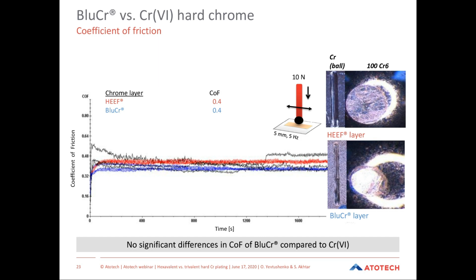This test is applied for determination of resistance to sliding, wear, and friction for non-lubricated or lubricated contacts. In this case, it was non-lubricated. For this method against a hardened steel counterbody, we obtained comparable coefficients of friction for blue chromium and HEEF surfaces. So we didn't see any differences.